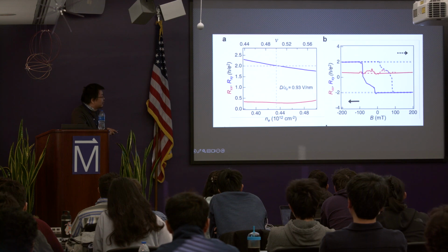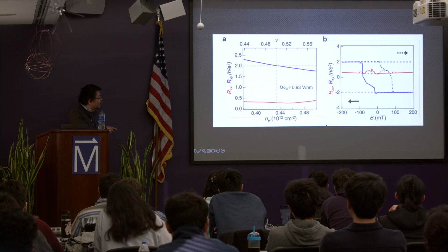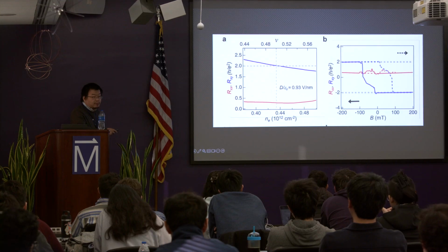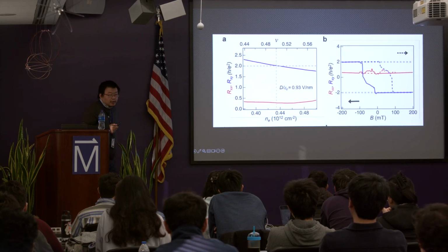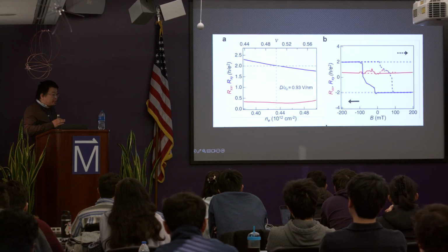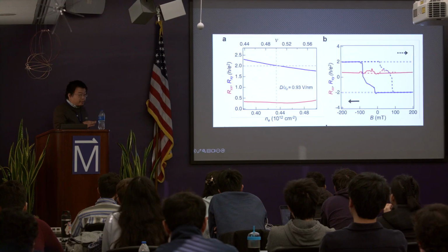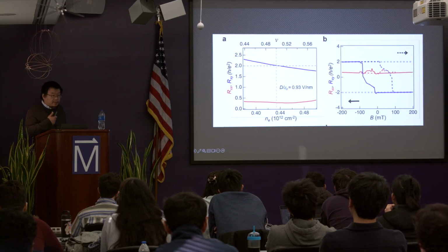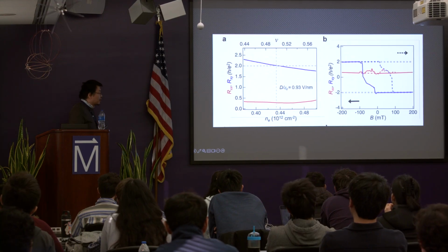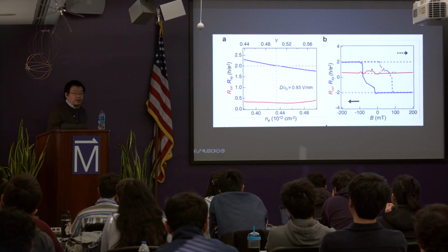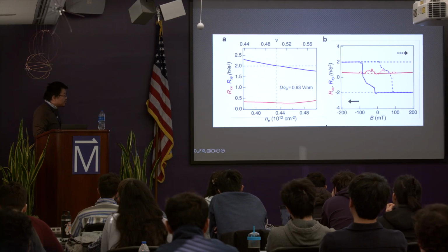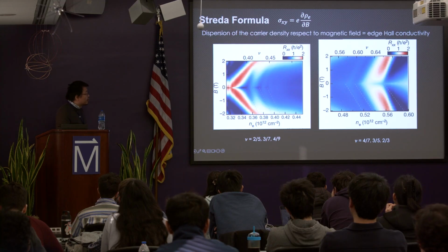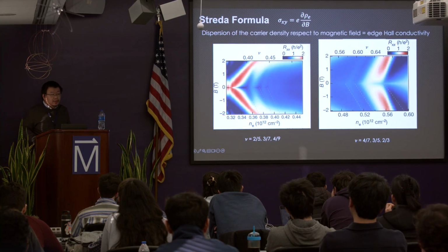Similarly, you could pick any point along this tilted line and do a magnetic hysteresis. You can claim anything. So basically, one needs to be careful in claiming all these states. You should have a really good plateau for Rxy, and a really well-defined dip for Rxx. In addition, this should also match the Streda formula. And you need to make sure the state is gapped.